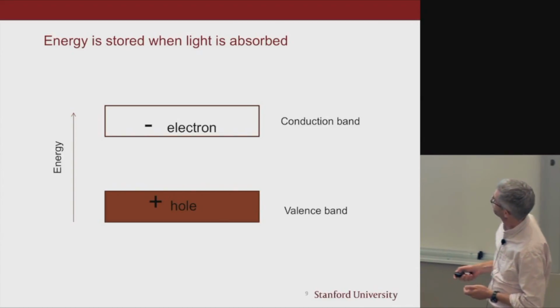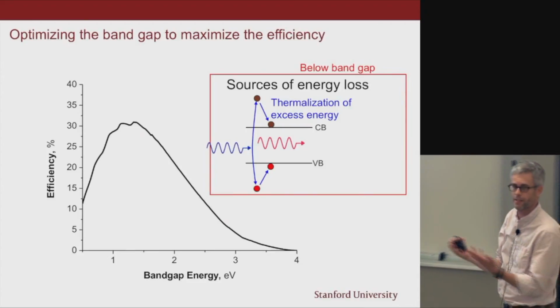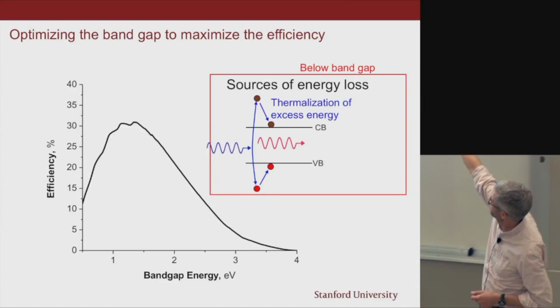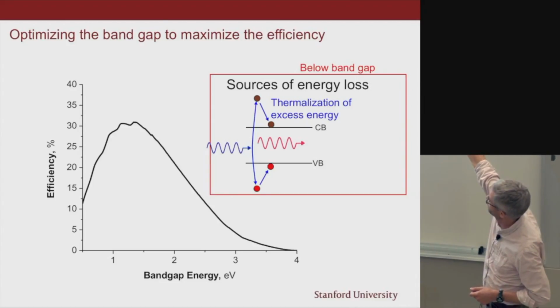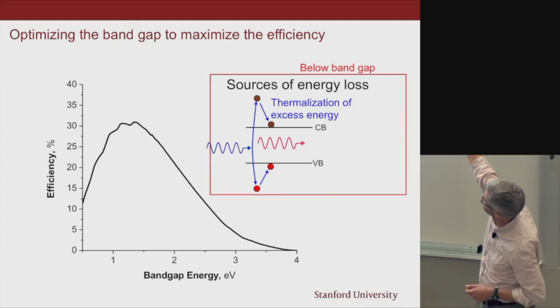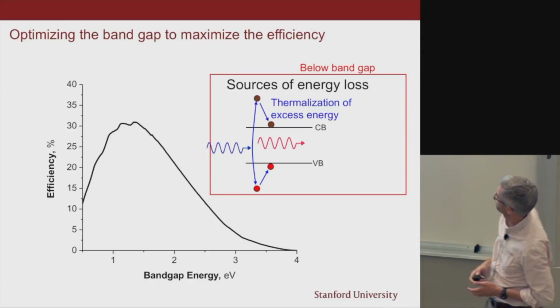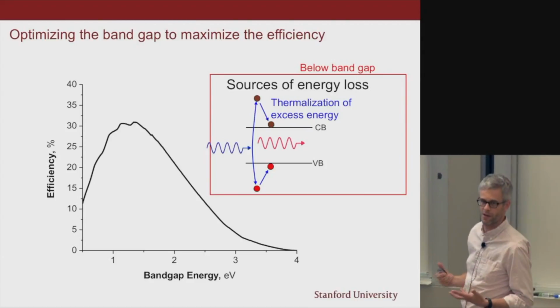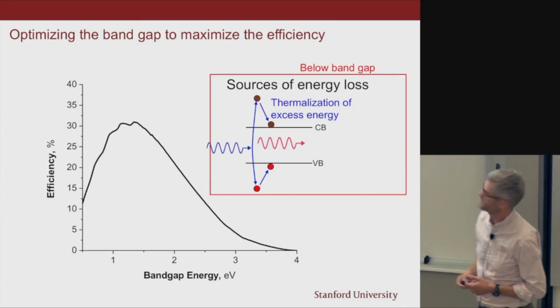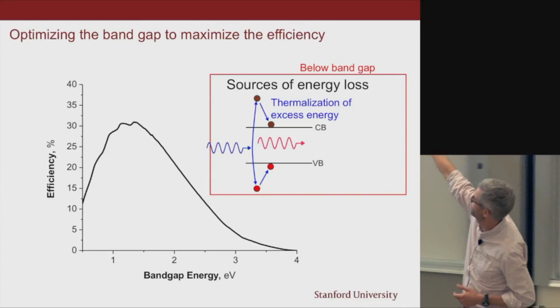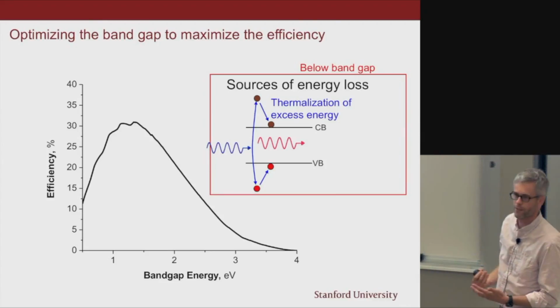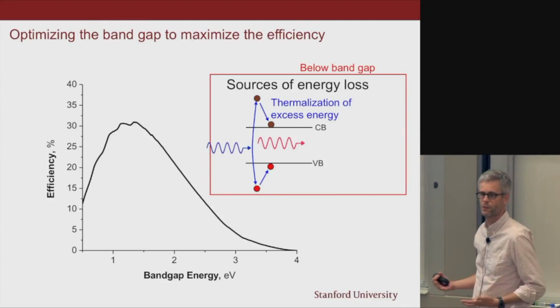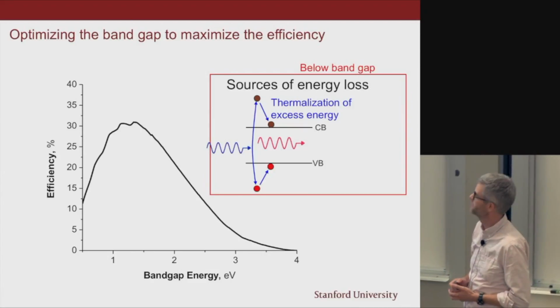When we do this, we want to get the highest current and voltage we can. To get a high voltage, we want the band gap to be large, because if we excite the electron high up into the band, it will fall to the bottom of the band and we'll lose all that energy. The voltage is somewhat related to that energy gap, and the larger it is, the higher the voltage we can get. So that may imply that we want a large band gap. The problem with that is we can only absorb photons if they have a greater energy than the gap. So if we pick a large gap, then a lot of the photons in the solar spectrum will go right through the solar cell unabsorbed.